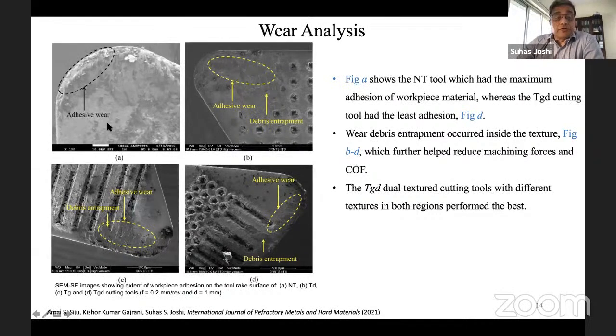Adhesion also gets reduced. So the first figure is the non-textured tool, and you find that there is a significant amount of addition of material on the surfaces, and that changes the geometry of the tool. The built-up edge which is formed actually slips over during the machining process, and it spills particles on the machined surfaces. And so the best one which is surviving in such a harsh condition is the dual textured kind of tool.